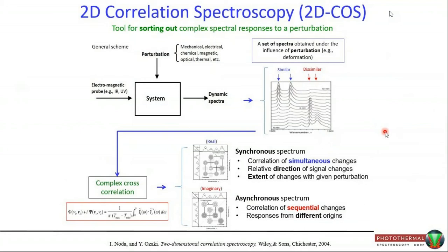We create a map to emphasize what part of the spectra is changing simultaneously in a coordinated fashion, and the part which is changing asynchronously, sequential changes. And these maps are created by applying cross-correlation analysis to the set of spectra. So the similar simultaneous part is described by spectra called synchronous spectrum. A sequential change part is described as asynchronous spectrum.